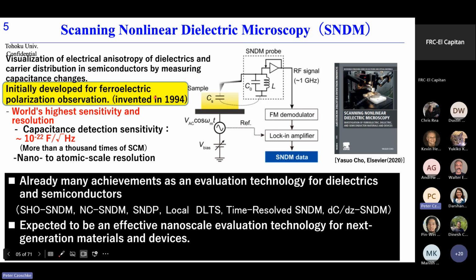As you know, the relationship of stored charge in a capacitance is Q equals CV, and C is quite constant. This means the nonlinear effect of dielectrics is quite small. So to detect such a nonlinear effect in dielectrics, the sensitivity of this microscopy technique must be very high. As a result, this microscopy has the world's highest sensitivity and resolution. The measured capacitance detection sensitivity is 10 to the minus 22nd farad per root hertz. This sensitivity is about 1,000 to 10,000 times higher than the world-famous scanning capacitance microscopy.